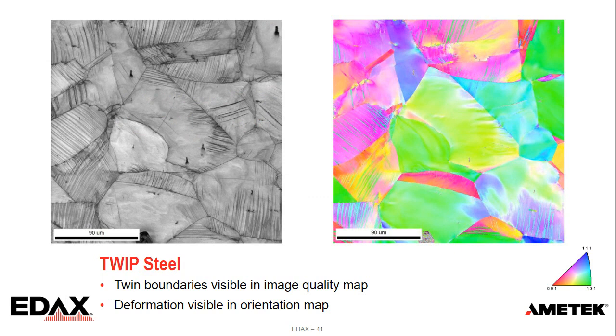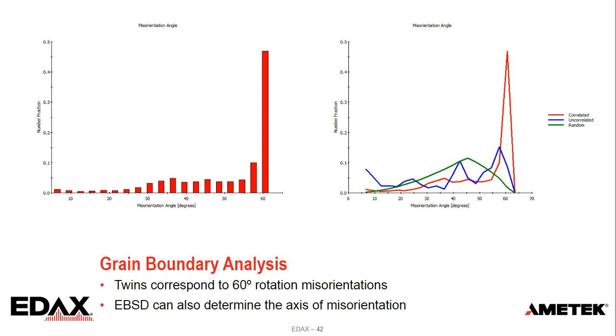I think they're really pretty just in terms of variation, but you can see it a lot in this bottom right one, where in the triangle it transitions from blue to greens. There's a lot of misorientation and twin boundaries present in these microstructures. We can measure this in more detail with what we call grain boundary analysis. The distribution on the left shows the misorientation angle distribution, the angle between orientations. You'll see there's a strong peak there at 60 degrees. That corresponds to our twins in the material, and we'll characterize that a little further because in addition to angle, we can also determine the axis of rotation.